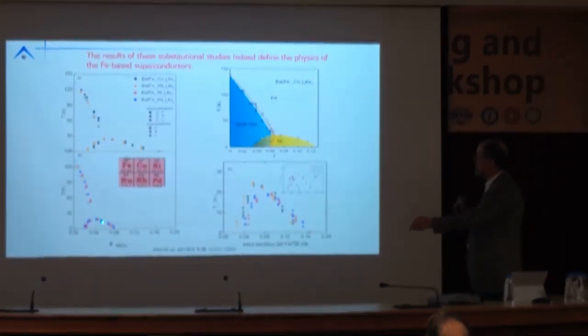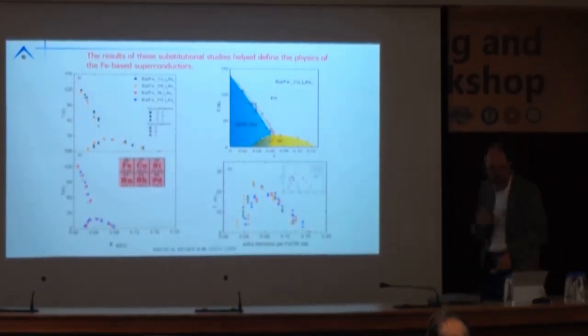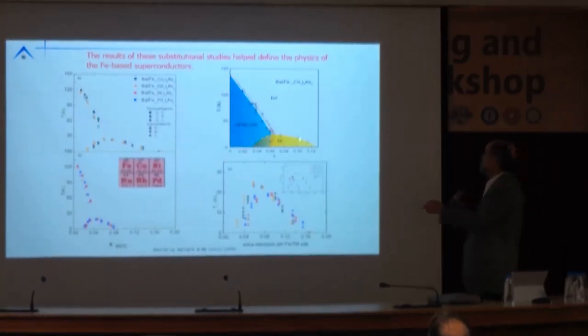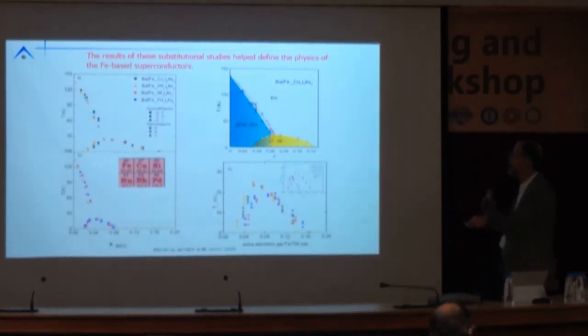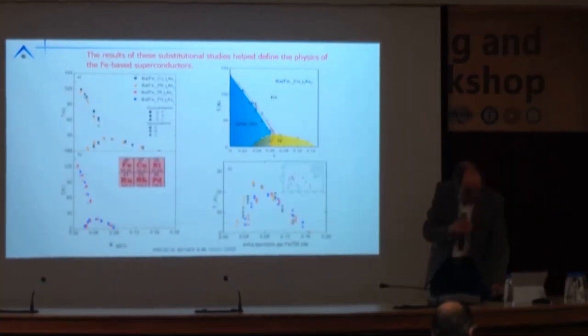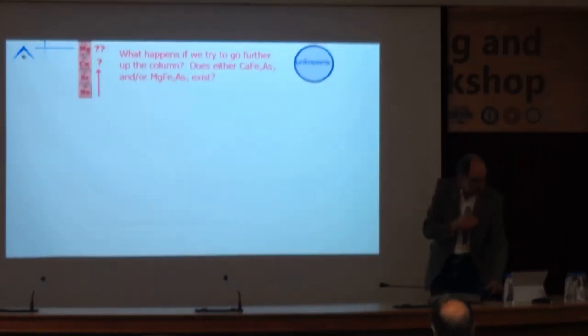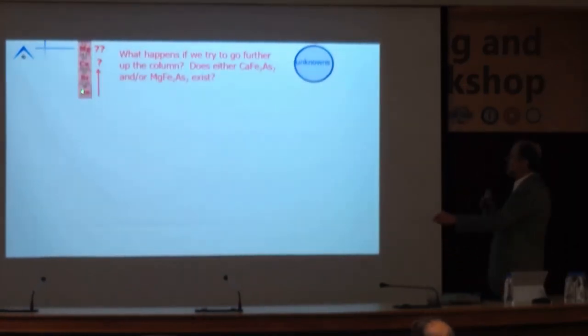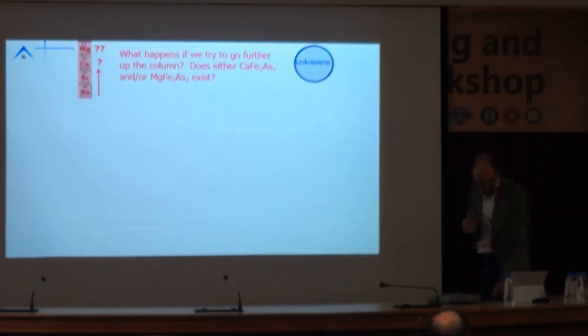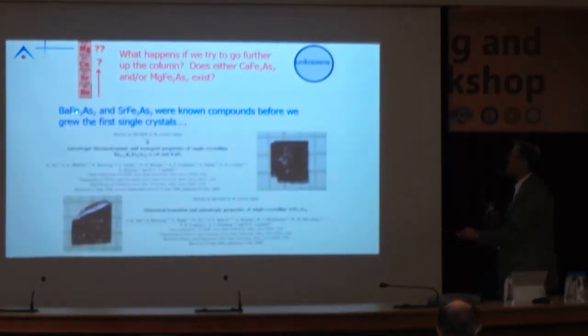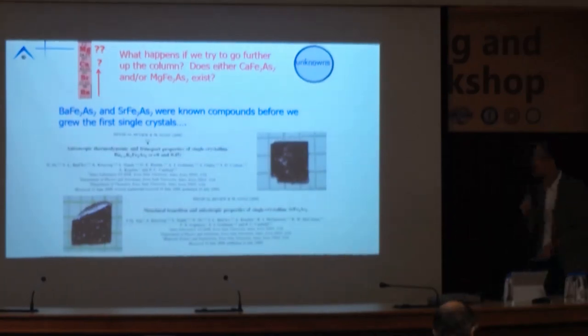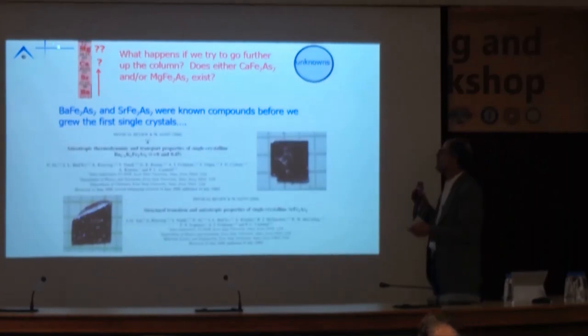For nickel and palladium, we see the same phase diagram, but basically scaled by a factor of 2, indicating that electron count is essentially the key parameter here. These studies help define our understanding of what are the rules for superconductivity in these materials. What's the relation between structural, magnetic, and electronic degrees of freedom? Okay. Now, unknowns. Well, we can have barium, we can have strontium. What about calcium? What about magnesium? Do they exist? The reason I say this is barium iron arsenide 2, strontium iron arsenide 2 were known compounds before iron-based superconductivity. On the other hand, there was no report of calcium or magnesium.